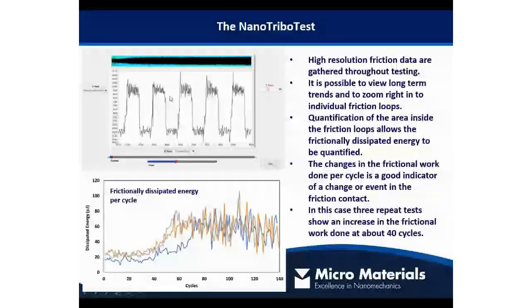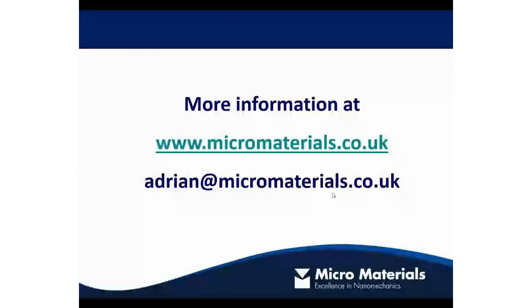So here's some example data. Again, our familiar kind of reciprocating tribometer friction versus sliding distance charts. We can convert our friction data into frictionally dissipated energy per cycle. And we can see with these particular systems, about 40 cycles at a pretty constant level of dissipation, then a ramp up, which signifies some significant change in that tribo system, possibly the onset of a complete failure. So that's just a very, very quick overview of the things we can do there.